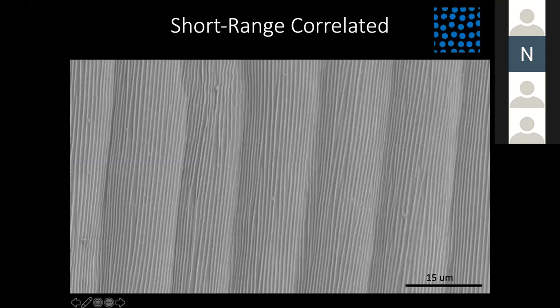Another interesting system is when you have still some correlation, but you start to have a little bit of disorder. This is called short-range correlated structure, because on the large range, you don't have correlation between the different points. But if you look at one single scattering element and you look at the neighbors around, more or less they have the same distance. And in the case of a one-dimensional system, this could be done. It's done, for example, in the surface structure of petals.